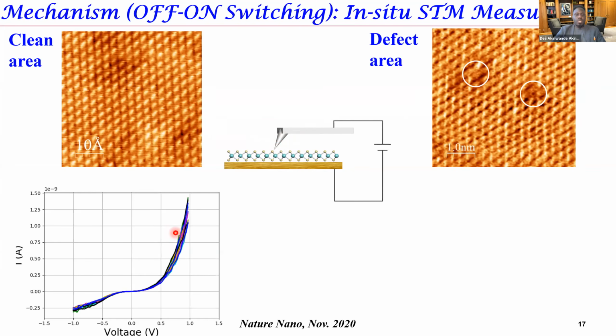So if you do transport, what you see is a kind of diode-like, nothing extraordinary, asymmetric curve. In this particular case, again, there's an asymmetry. This MoS2 is sitting on a gold film, and the STM is a gold tip. Even though the elements are the same, the geometry is different.